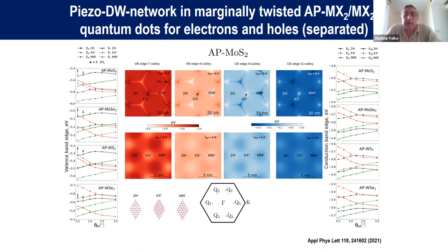And at the same time, when we look at the electrons, which may be in the K point or, due to interlayer hybridization of orbitals, at another local minimum in the Brillouin zone, which is called the Q valley, we also get the minima of the energy in the corners of the domain wall network.